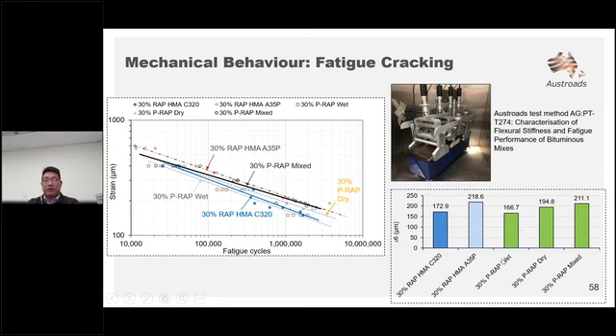The reason behind that was, if we recall the previous report, the 30% of PRAP in wet method was produced with the fresh binder C170, and the mix with C170 has an epsilon 6 slightly lower than a hot mix C320. It could be inherited from that result to the PRAP, and it led to the result of the 30% PRAP wet method being slightly lower than the 30% RAP hot mix with C320.